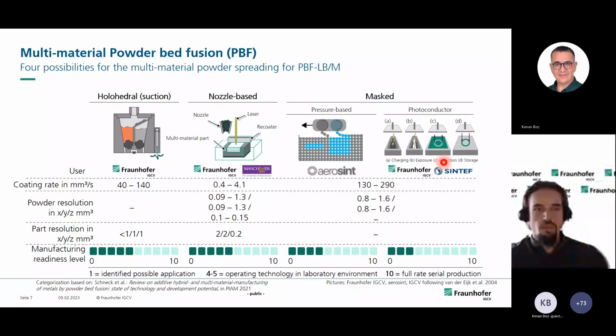So here we've got some data. This was based on a review paper from my fellow colleagues, which was published in PAM in 2021. If some of you may be interested in that, here's the source. So you must distinguish this, especially regarding the coating rate. Here, this system actually has a rather high coating rate, but it's limited due to the fact that it must run over the build plate twice per layer.